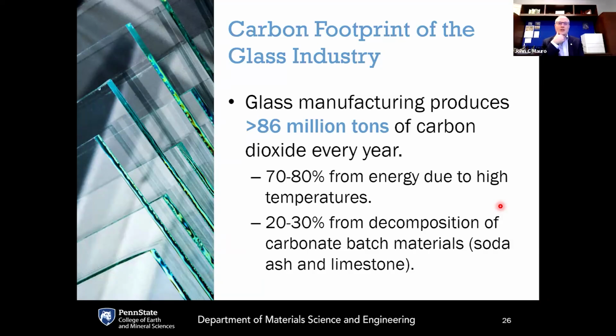The problem that we're trying to address here is the carbon footprint of the glass industry. Every year, the glass industry produces over 86 million tons of CO2. About 70 to 80% of this is due to the energy consumption because of the high temperatures that are required for melting, and about 20 to 30% is due to the decomposition of carbonate batch materials.